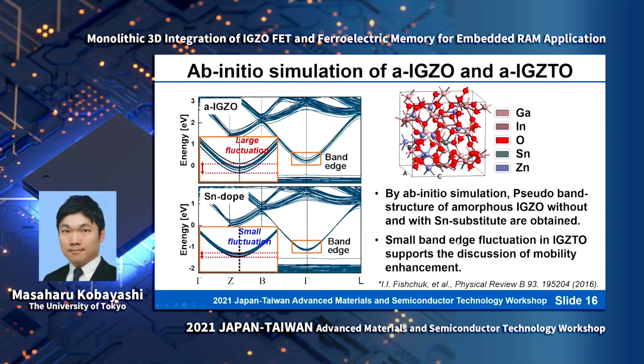And to verify this discussion, we conducted very preliminary ab initio calculations. First, we made an amorphous model using the melt and quench method by molecular dynamics simulation, and then we created a supercell for the amorphous semiconductor for both IGZO and IGZTO. Then we calculated a pseudo band structure for such amorphous unit cells, and we simulated roughly 10 samples